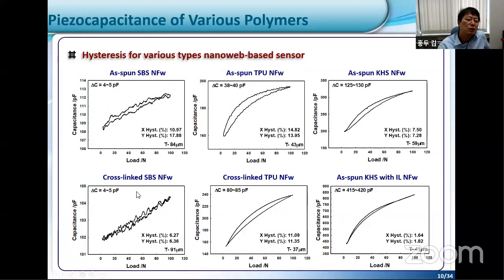As you see, the SBS looks so good, but as I told you before, the sensitivity is not good enough. In the case of TPU, if we cross-link, then the hysteresis goes down from 14% to about 11% or 10%. As you know, in a normal polymer system, even though it is a very elastic material, about 10% hysteresis is very normal. But we tried to overcome this kind of behavior.